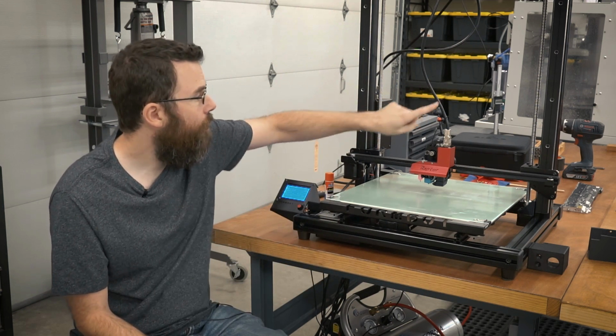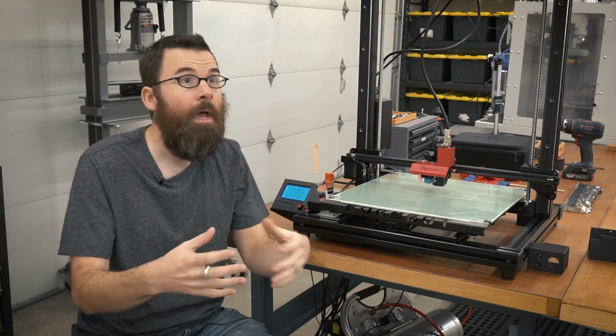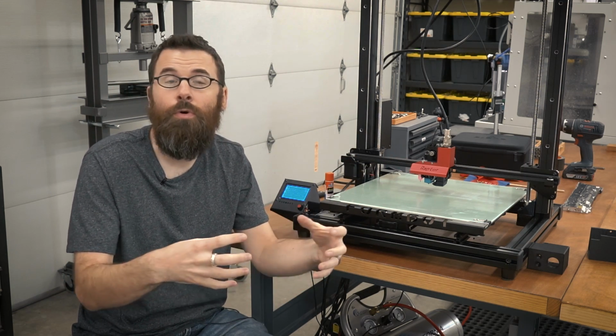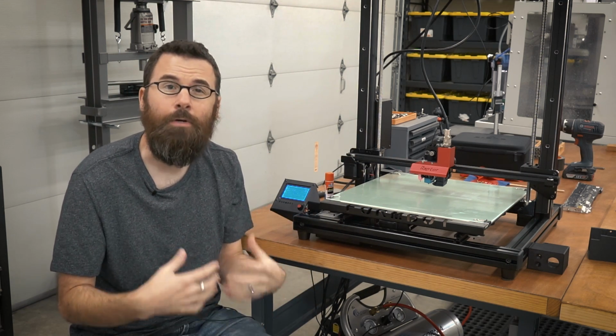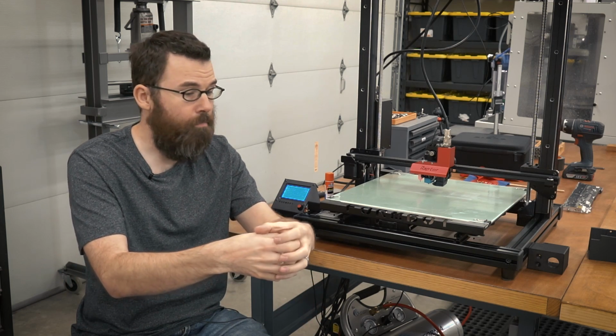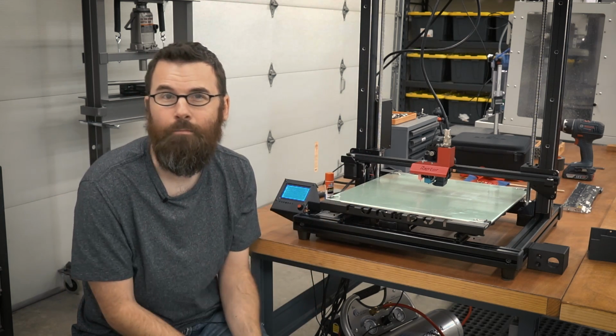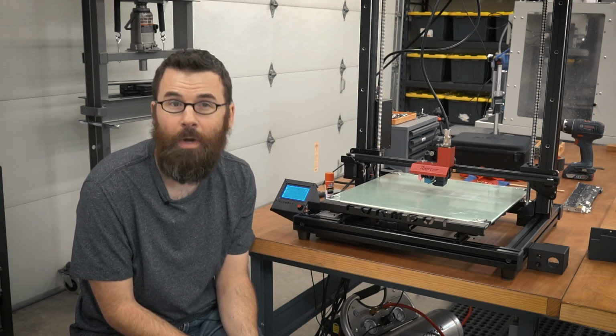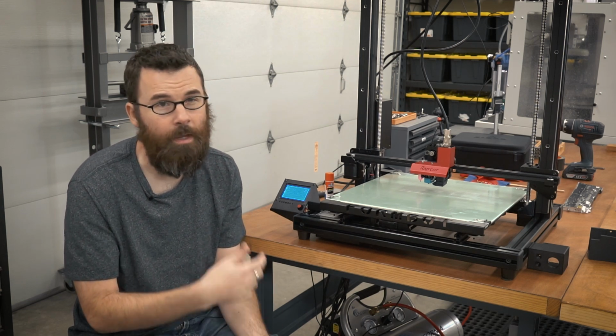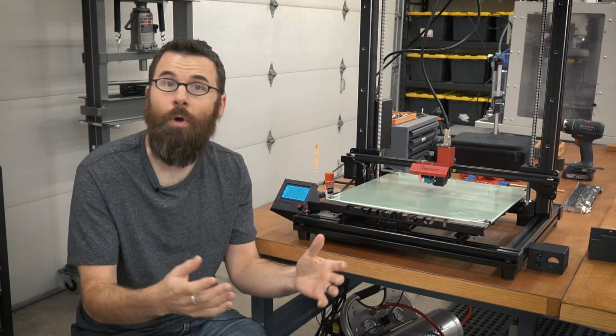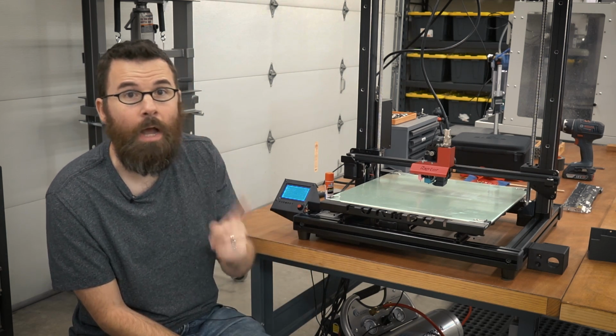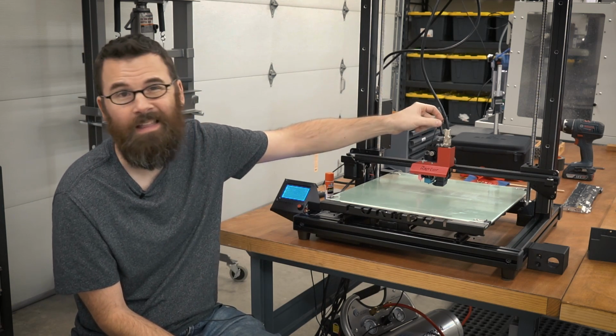That means when they run through your nozzle, they are going to basically sand away or erode away the nozzle. So if you use a standard brass nozzle, it will get bigger and bigger and bigger, and then you're going to have problems. And it's pretty quick, actually. I think just even like a quarter of a roll can destroy your brass nozzle. So do not use a brass nozzle with Nylon-X.